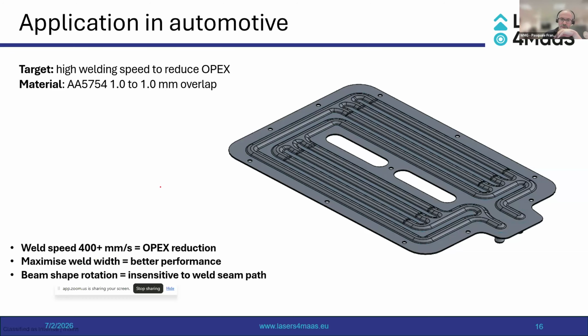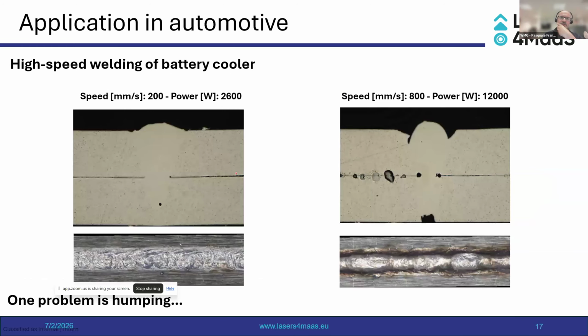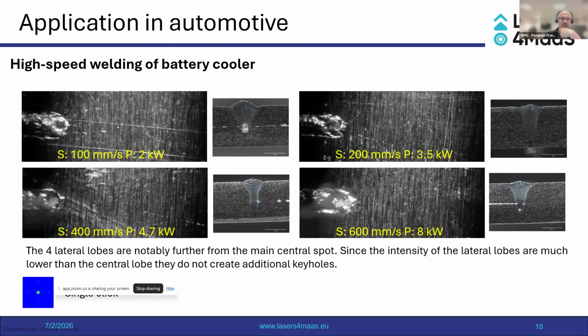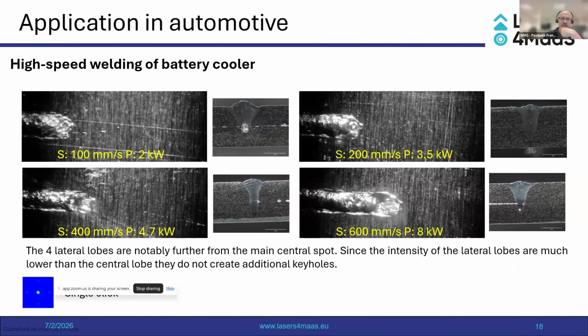second. That is very challenging because with high speed welding on aluminum, when you cross 200 or even 300 millimeters per second, let's say that is a threshold, you start getting this humping profile, which is a defect on its own. You have undercuts, you have stress concentration, you have porosity. You are losing penetration, and it's basically an unstable weld. So that is a problem with this application, and this is where dynamic beam shaping comes into play.